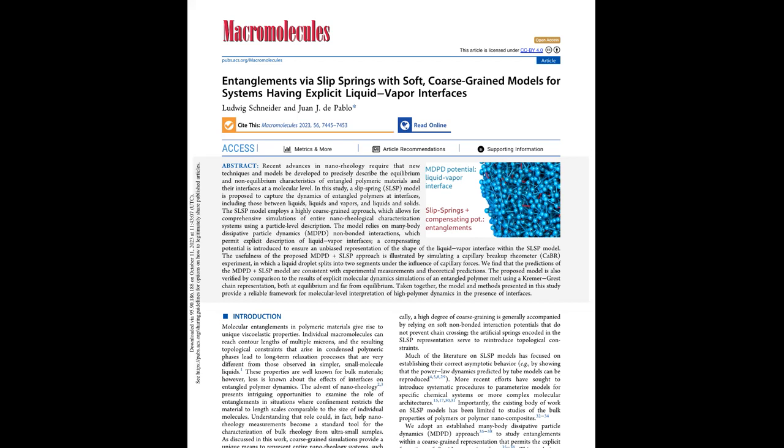Furthermore, during filament thinning and breakup scenarios, the SLSP model reproduces the characteristic dynamical regimes observed in KG simulations, including linear neck thinning, followed by entanglement-controlled exponential decay. Quantitatively close relaxation times suggest that this coarse-grained approach enables accurate rheological predictions while requiring substantially less computational effort.